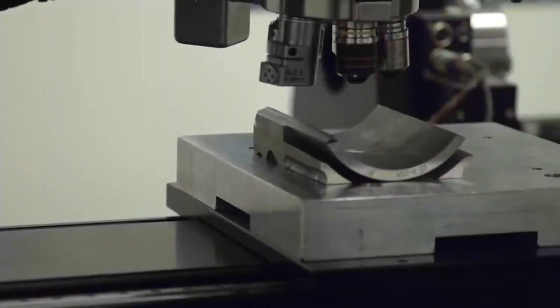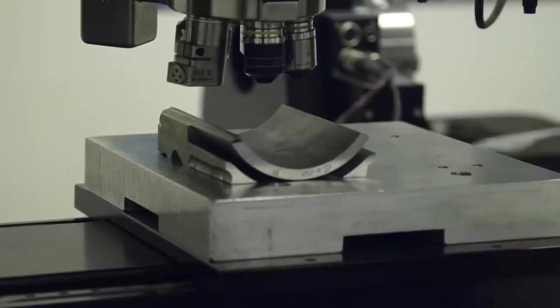The only other thing to watch out for is if the material is composed of any multi-layers of films that are somewhat transparent, then that can cause some trouble. Since we're using an optical instrument, the light kind of goes through those transparent films and causes some problems. So you have to be a little bit aware of that. Other than that, as long as it can fit under a microscope, that's why I usually say to customers, if you can look at it under a microscope, I can probably measure it.